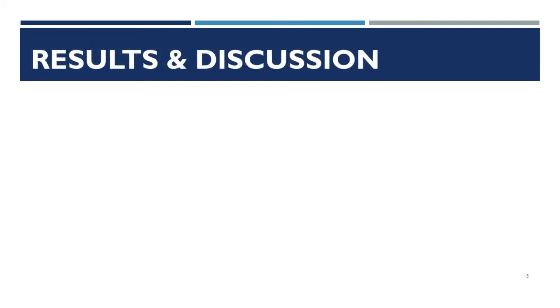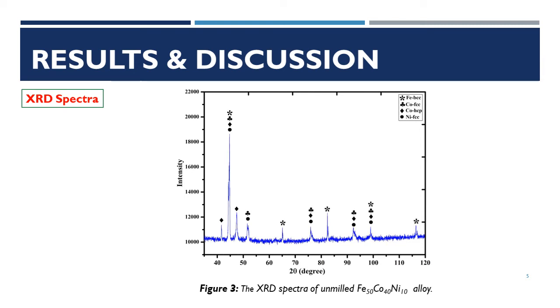We start the part of results and discussion with the X-ray diffraction spectrum of the unmilled powders shown in figure 3, which reveals all the expected starting element peaks. As shown, the non-alloyed sample is composed of iron with a body-centered cubic structure, nickel with a face-centered cubic structure, and cobalt with two allotropic structures, face-centered cubic and hexagonal close-packed.